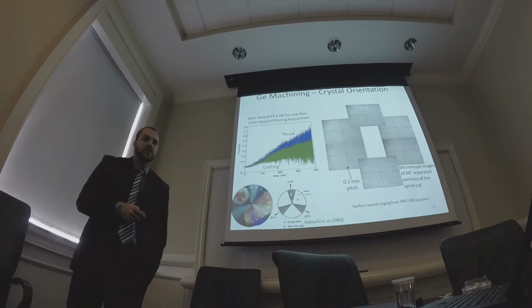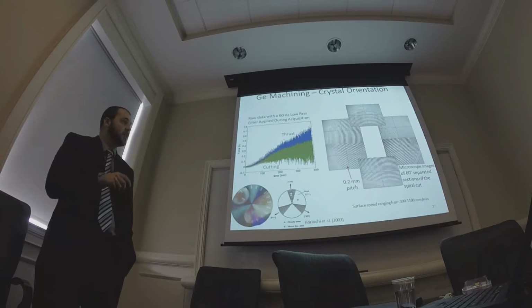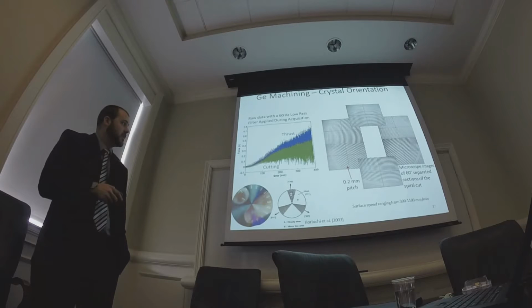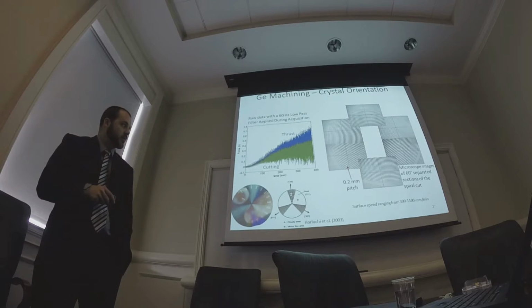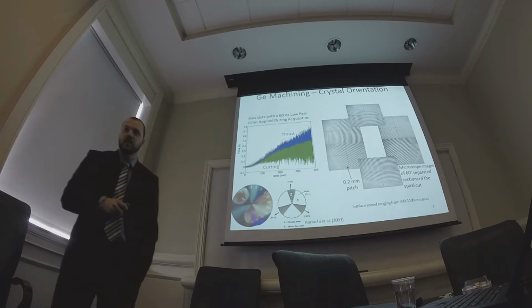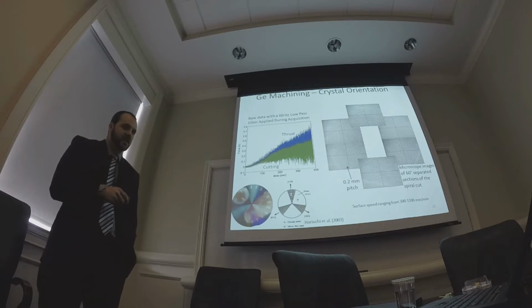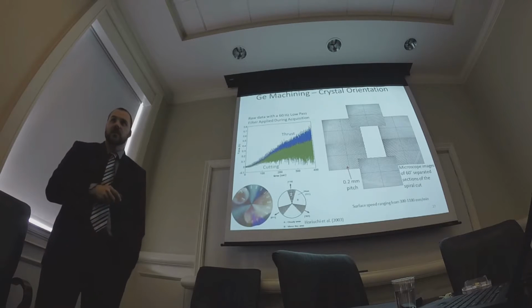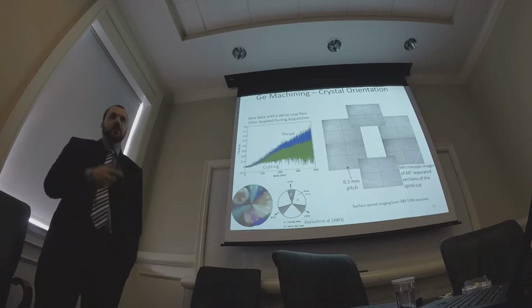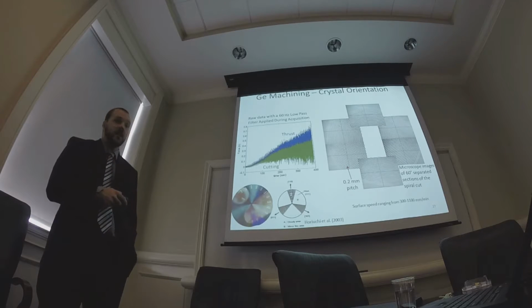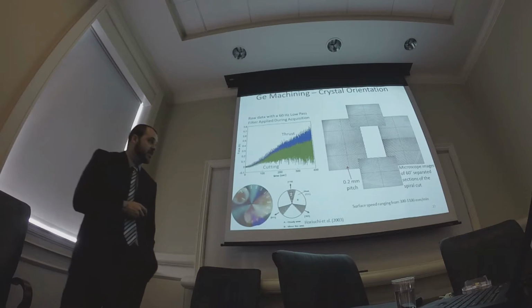Now I want to show the crystal orientation. This is results from the round nose planing that we did. Horiyuchi showed in his paper this 3-fold symmetry that you see in germanium when you turn it. You get 3 sections that show significant fracture before these other regions would show fracture. If you go more aggressive, eventually this will start to fracture too, but these 3 regions will fracture first.